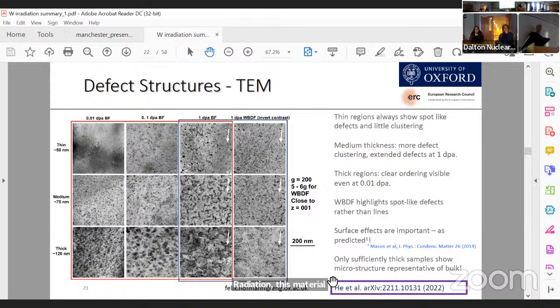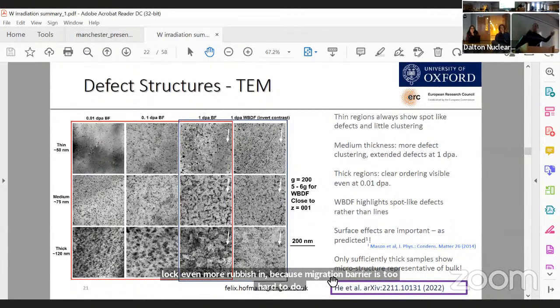because you prevent separation of your vacancies and interstitials. You keep them close enough together that hopefully a reasonable portion may eventually recombine. In practice, whether that happens, or whether you just lock even more rubbish in because the migration barrier is too high for them to make their way a few unit cells back together, who knows? Don't know.